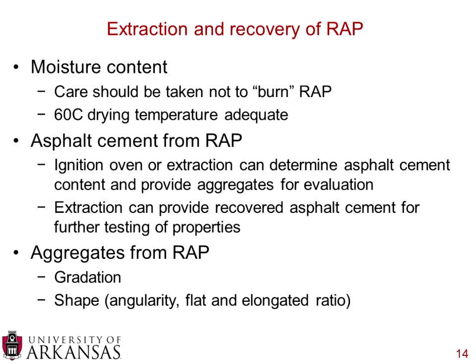Because it's added later, it doesn't get as much drying as the virgin aggregate does. And this is something that you want to mimic in the lab. You want to make sure that you do not, one, burn the RAP. If you heat RAP up too hot, you can actually further oxidize and burn the asphalt cement. And you also want to make sure that you get all the moisture out of there. And this can be done by drying the material at about 60 degrees Celsius.